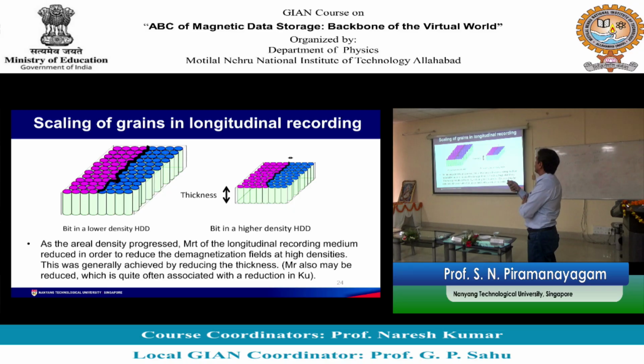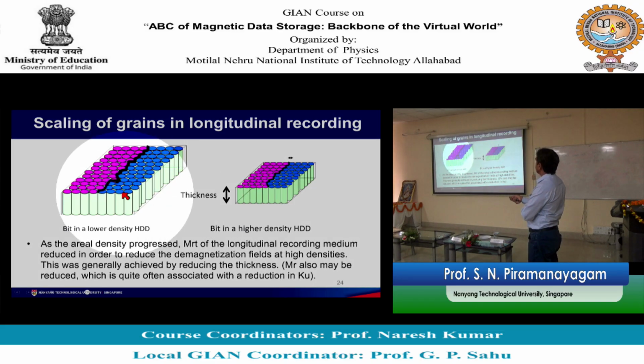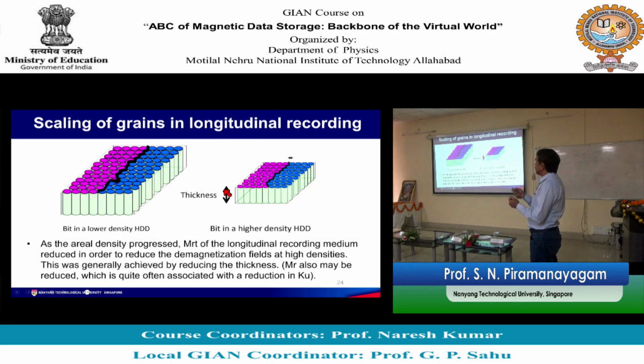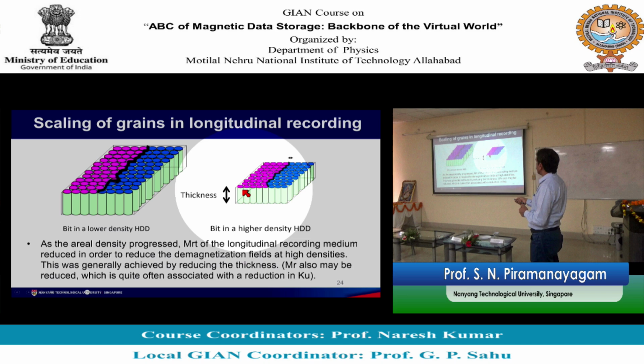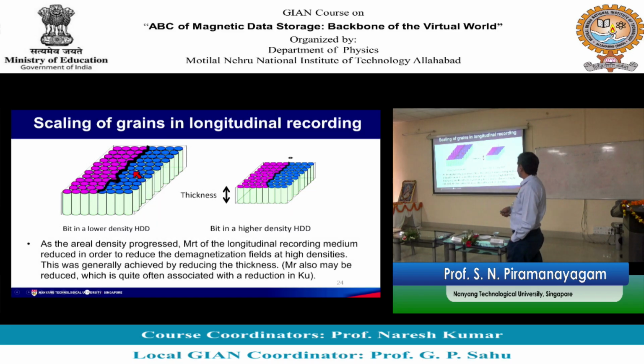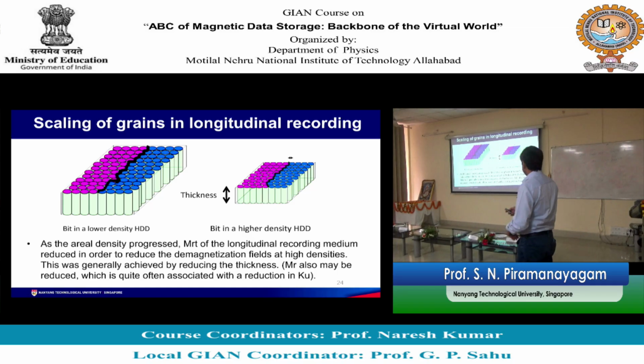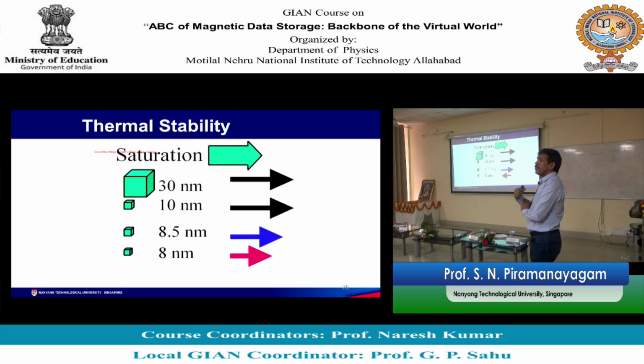So by scaling, what did we do? We kept reducing the thickness. We went from a larger thickness to smaller thickness, and we reduced the grain sizes. So we make larger diameter to smaller diameter grains and so on. If you look at the bits in a lower density hard disk drive and higher density hard disk drive, they will be shorter in height and smaller in diameter. Bit length is less compared to here, track width is less compared to here, and so on. So this is what we have been doing with the scaling, and this leads to a problem called thermal